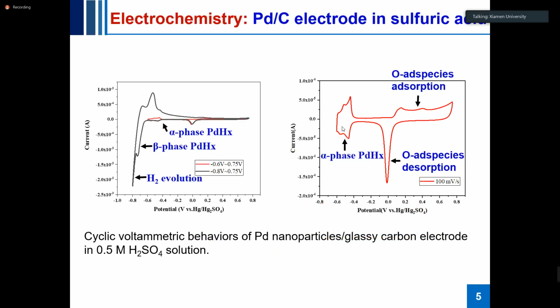This is much stronger than the interaction in the alpha phase, which is actually the adsorption bond. So this is the electrochemistry of palladium nanoparticles carried by a glassy carbon electrode in a 0.5 molar sulfuric acid solution. In the whole cyclic voltammetry, we can see the small peak shown in the right line. This is the alpha phase hydrogen, and the second peak is the beta phase hydrogen. And after that, if the potential goes negatively, we can see the hydrogen evolution on the palladium nanoparticles.